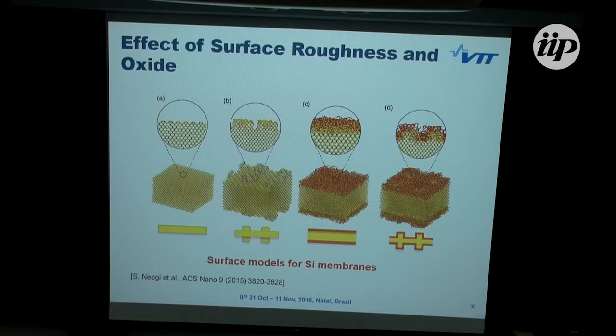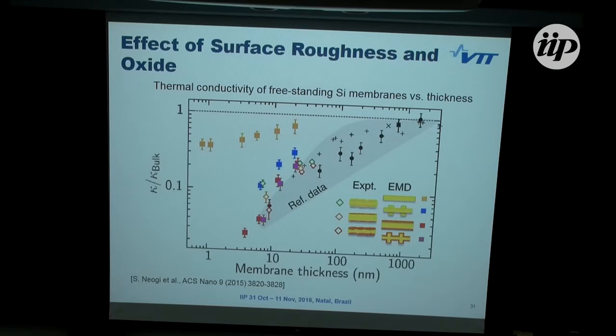And then there are the clean, a little bit undulating surface, and then the sheer oxide. And this was already shown by Davide. So the thickness itself doesn't make too big a difference. If one goes to very thin membranes, the thermal conductivity doesn't change too much. But when one puts in the oxide, it goes very strongly down, and then adding this little surface corrugation, undulation, still decreases the thermal conductivity a little bit. And as explained by Davide, these open diamonds are experimental data. This is after HF dip, which removes the oxide but doesn't touch silicon. So these are more or less equivalent samples.